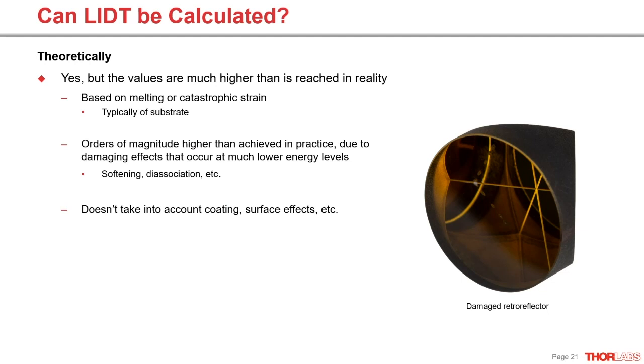One question we do occasionally get is, can damage threshold be calculated in a theoretical sense? I know this is my substrate, these are my coating materials, can I just plug this all into a formula and get a number? And the answer is yes, but not really. You will get a number that's at least an order of magnitude higher than is typically tested. That's because these calculations are built based on the melting or catastrophic strain to failure of a typical substrate. And you're going to see damaging effects long before that. In glasses, you may get softening, and in some crystals, you can get dissociation.